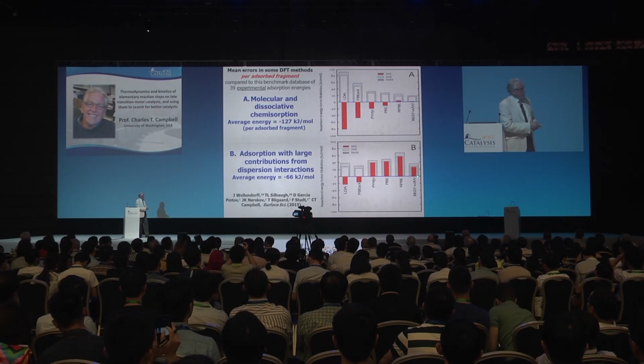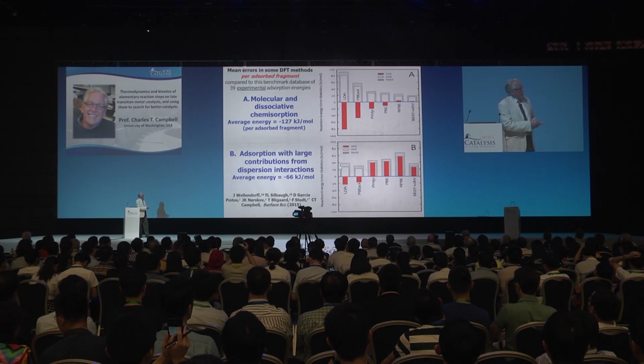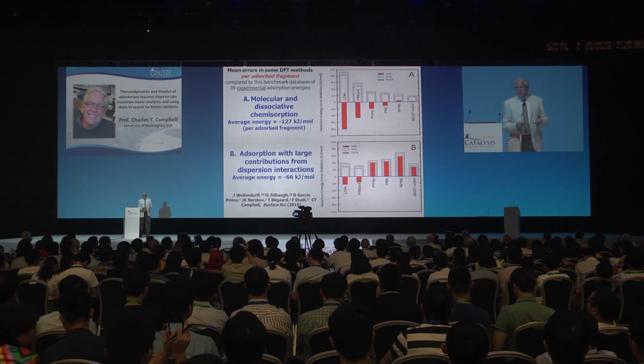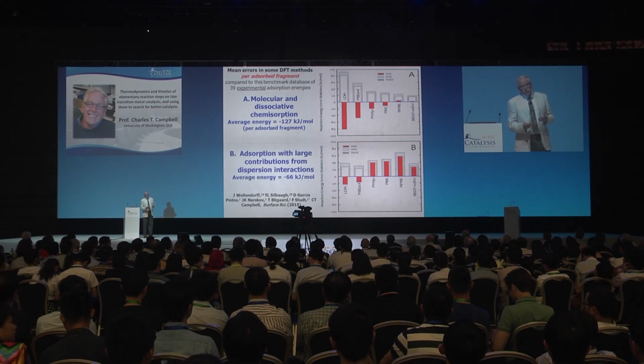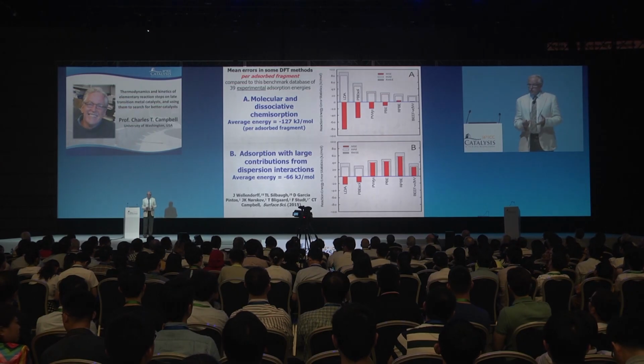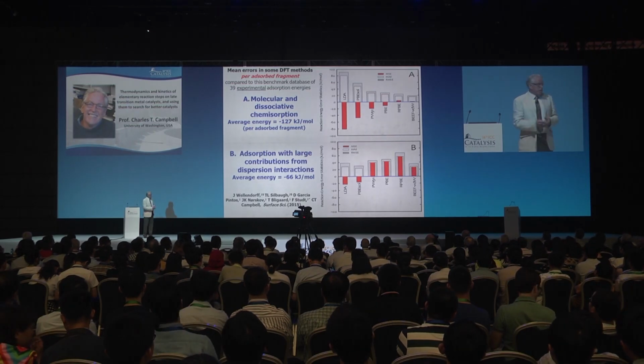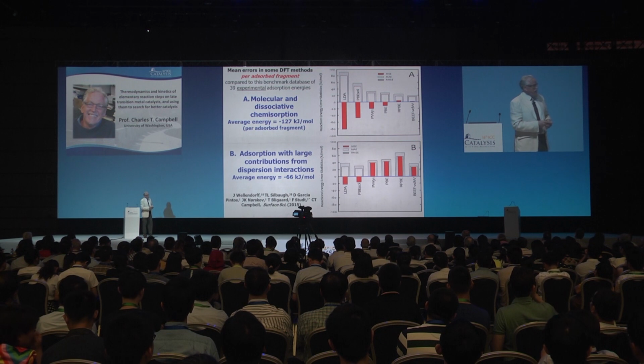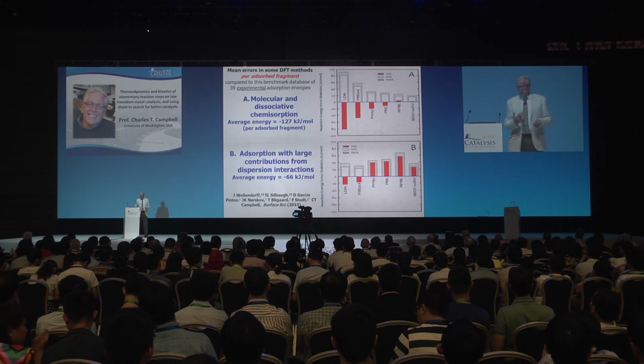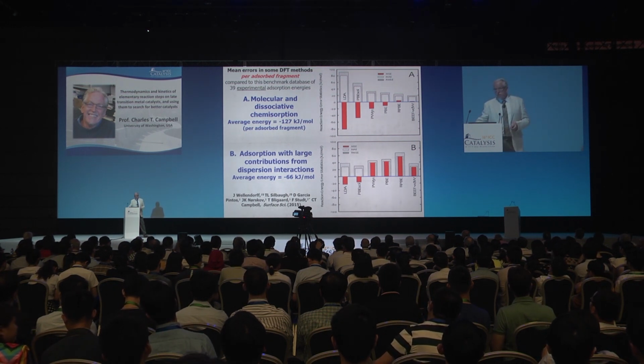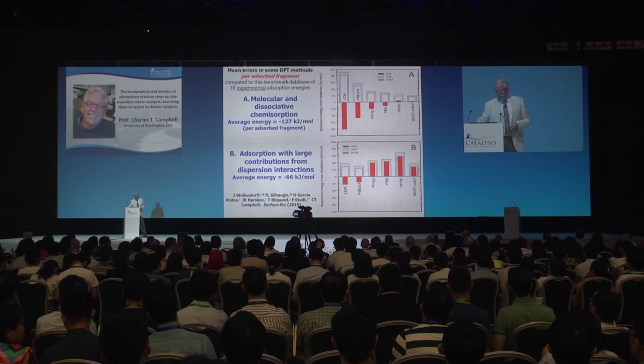So it's especially when there's large contributions from van der Waals interactions. And these are the errors per adsorbed fragment. So if it's a dissociation reaction, you actually have to multiply those errors by 2 to get the real error for the dissociative adsorption reaction.